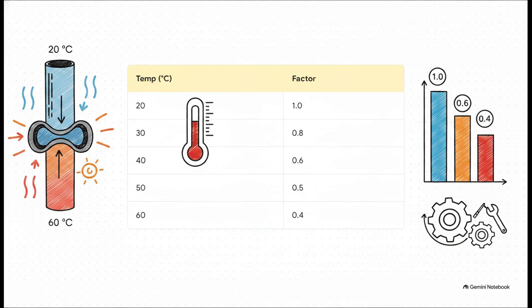Furthermore, as engineers, you're expected to calculate system parameters based on actual operational environments. Based on standard temperature compensation calculations, at an ambient 20 degrees Celsius, our pressure rating factor is a perfect 1.0. But notice how elevated ambient temperatures rapidly degrade the tensile strength and pressure capacity of polyethylene pipes. By the time the conveyed fluid or ambient environment hits 60 degrees Celsius, the pressure rating reduction factor drops to 0.4. Think about what that means in practice. A pipe rated for 16 bars at 20 degrees can only safely handle a fraction of that pressure at 60 degrees. Your welding parameters and overall system designs must account for these thermodynamic realities.